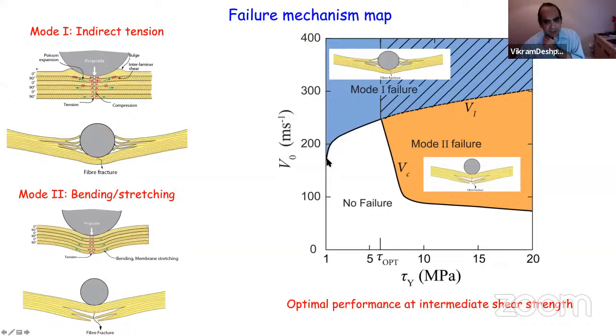You'll do reasonably well, but as you increase the shear strength a little bit, you maximize the ballistic limit, because at this shear strength you're going to get failure at, say, 250 meters per second. But if you increase the shear strength any further, you hit this mode 2, which is the bending failure mode, and it reduces the ballistic limit very substantially, and you're now going to get poor performance. So it's very interesting. It's telling you that it's not sufficient to have high fiber strength, but you need an intermediate shear strength to actually get the optimum ballistic performance in this case.